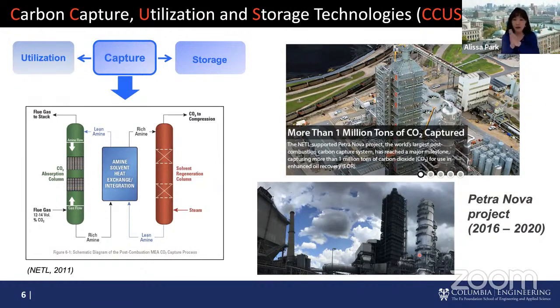And then you're regenerating the solvent in this red-colored reactor, the solvent regeneration column, by putting energy in so you can release the CO2 and regenerate the liquid solvent, which you can recycle back into the CO2 capture reactors. So you can imagine that if you have a strong binding energy towards the CO2, your reactor, the green reactor, which is the CO2 absorption column, will have faster reaction kinetics and be smaller. But at the same time, the stronger the binding energy, the more energy penalty you pay in this regeneration reactor to release that CO2 back out. So there should be some optimization of how strong that binding energy has to be.